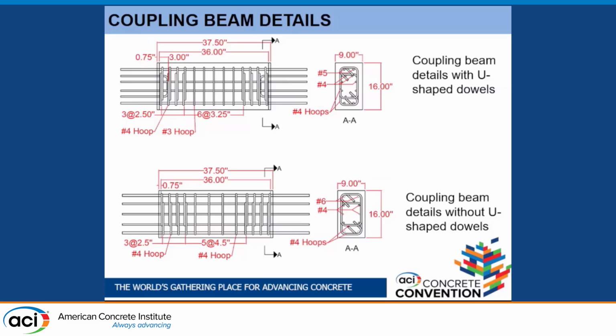These are made of fiber concrete, and typically the walls are made of reinforced concrete, regular concrete. So we're going to have a cold joint, either because we put some sort of mesh to block the fiber concrete from going into the wall if we cast in place, or because we precast the coupling beams. In the lab, we prefabricated the coupling beams, so what you see is the fiber concrete part, the bars stick out.